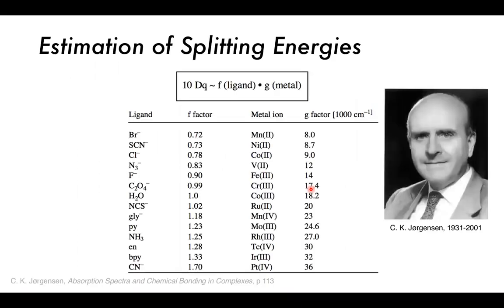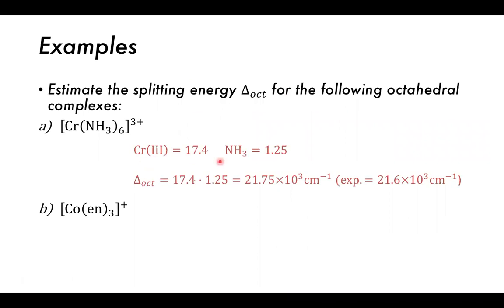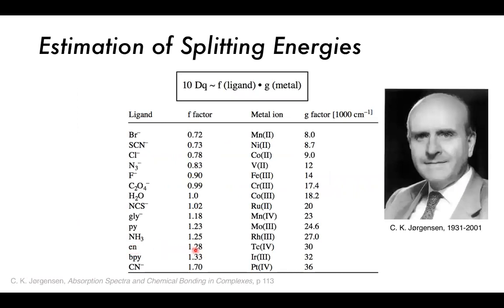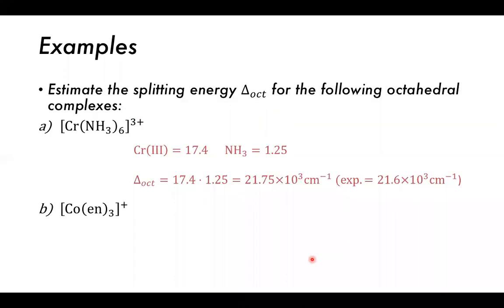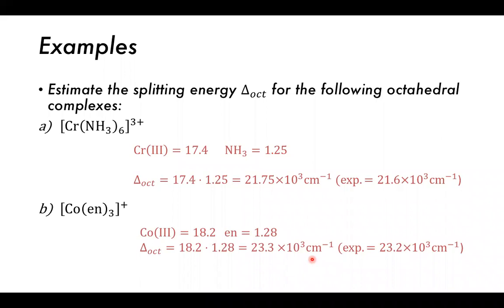So for the chromium, if we look back at our table, chromium 3+ has a g factor of 17.4, and then ammonia has an f factor of 1.25. So we then calculate those, we fill it in. So 17.4 times 1.25 will give us a delta octahedral splitting estimation of 21.75 times 10 to the 3, or 21,750 wave numbers, which is remarkably close to the experimental value. Then for cobalt, ethylene-1,2-diamine. So en is 1.28 for its f factor, and cobalt is not here, but we can find it in tables of data. Or sorry, it should be cobalt 3, which is 18.2 times 1.28. Multiply those together, and we see that they're very close to each other as well.